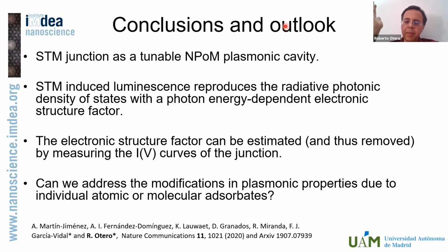If you place something in between the tip and the sample by placing some molecules in between, you have two different possibilities. The first possibility is that you place the molecule directly in contact with one of the metallic electrodes. In this case, the main problem is that people have tried to measure the plasmonic response depending on whether you inject on the molecule or somewhere else. But the truth is that nothing is very clear. And we believe that nothing is very clear because when you inject through the molecule, the electronic structure changes completely. So only by following a normalization approach like the one that we are proposing here would I expect to see anything that truly makes sense from the optical point of view.